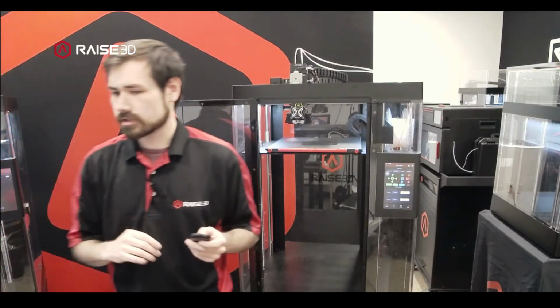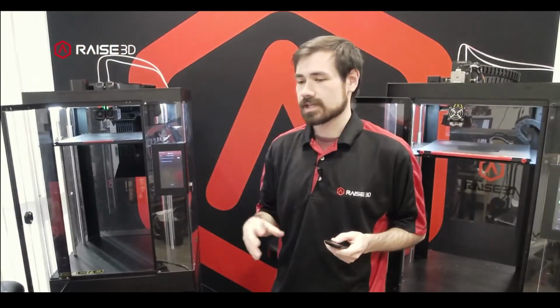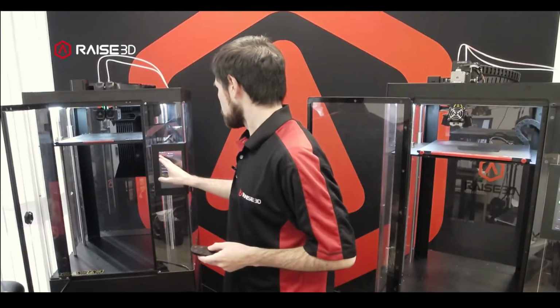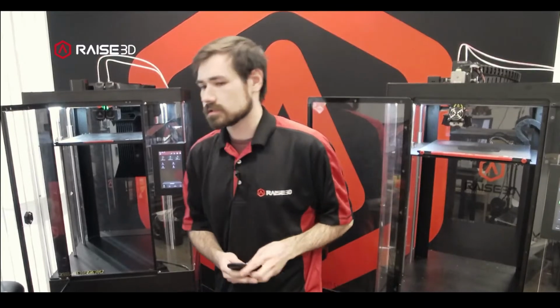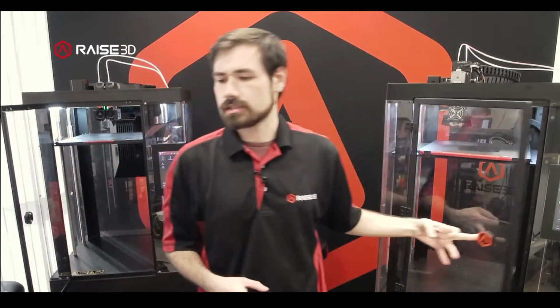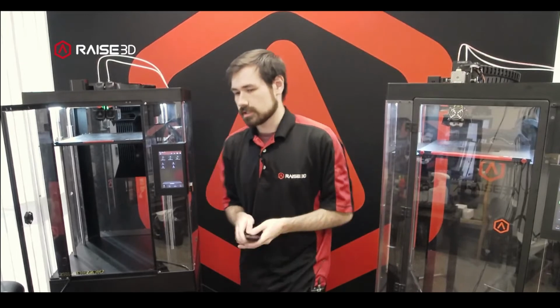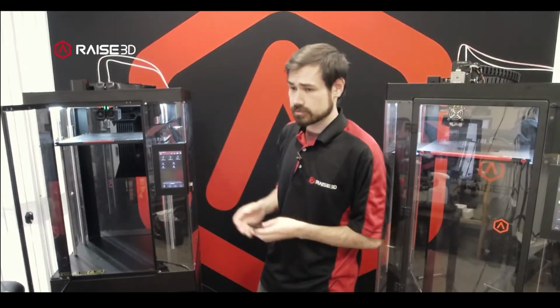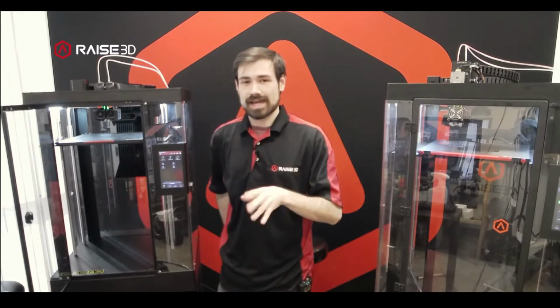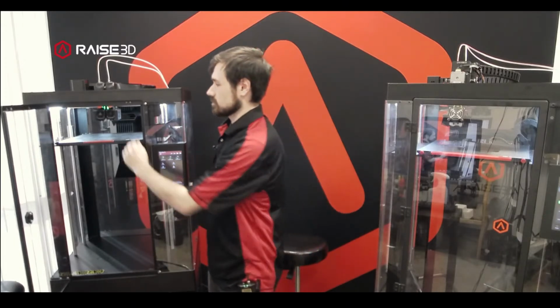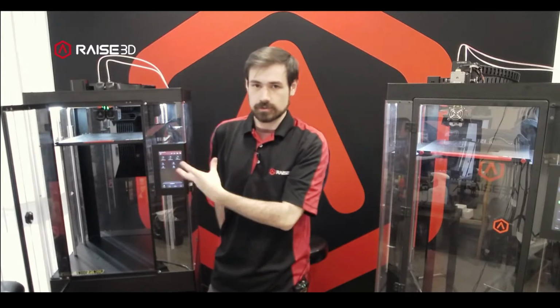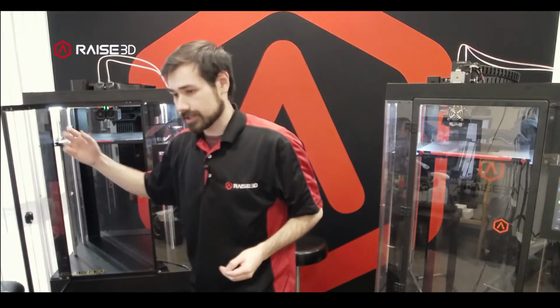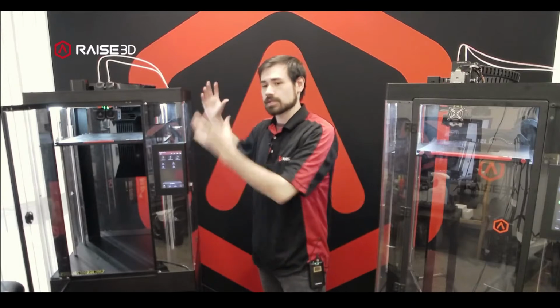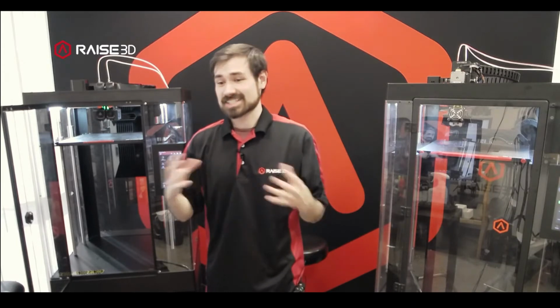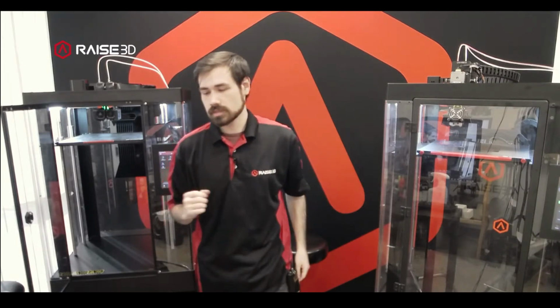And then we did have another question. How hot can the chamber get on the Pro 3? And that is something we don't actually measure, or it's not an actively heated chamber on the Pro 3 machines. It is passively heated by the bed. So we'll set the bed temperature to 60 or 100 C, and then with the lid on, it's just going to be the ambient temperature around that. So I would expect it to be close to 100 C, but not consistently holding 100 C the entire time.